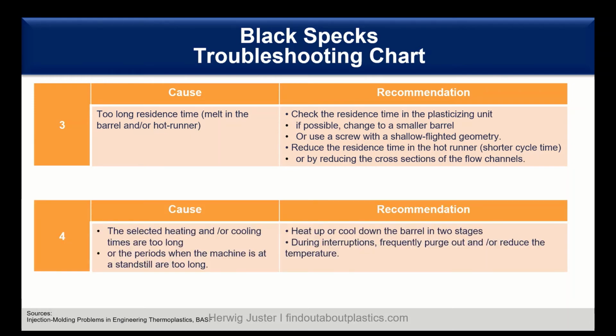Another temperature related cause is that the heating and cooling times are too long, and also periods where the machine is at a standstill are too long. So here one idea is to make the heat up or the cool down of the barrel itself over stages. For example, 2 stages is usually sufficient. Or when we have the case of interruption, purge the barrel, purge the hot runner, and reduce the temperature. For example, also in polycarbonate, you can always reduce the temperature during standstill and then heat it up again.